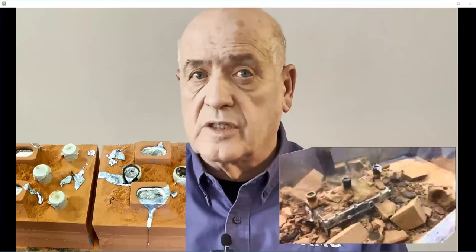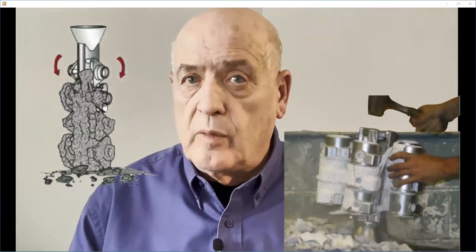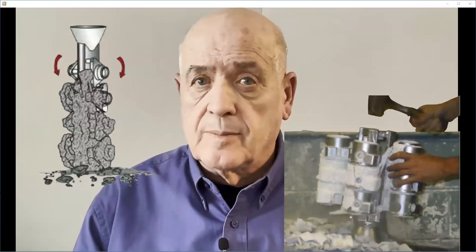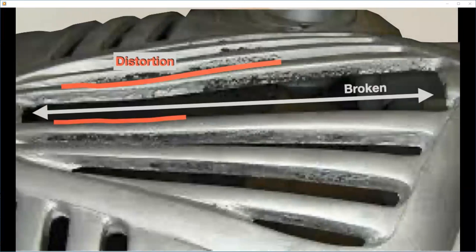Perhaps surprisingly, finishing begins when the casting is still in the mold cooling. At this point, the foundry and pouring teams are less interested in the casting and more interested in moving the molds to shakeout in the case of air-set sand castings or to ceramic shell removal in the case of investment castings. However, removing the casting from its mold too quickly risks distortion of the thin walls and delicate projected casting features. Such distortion will immediately violate as-cast dimensional tolerances, and the idea of protecting the as-cast surfaces has already been